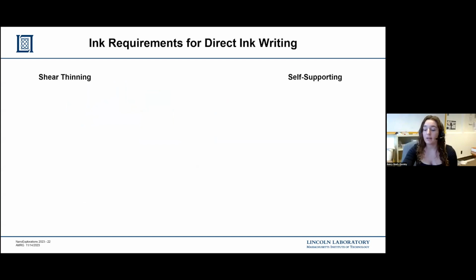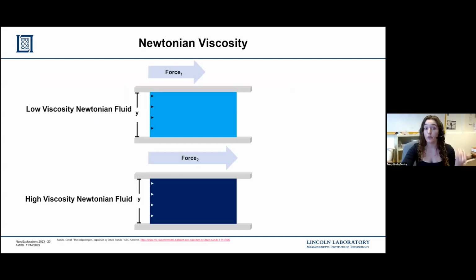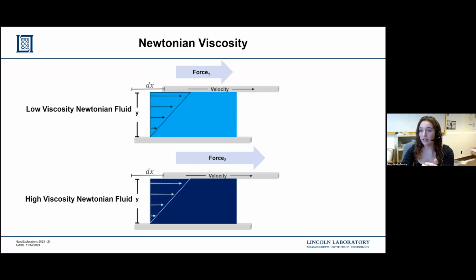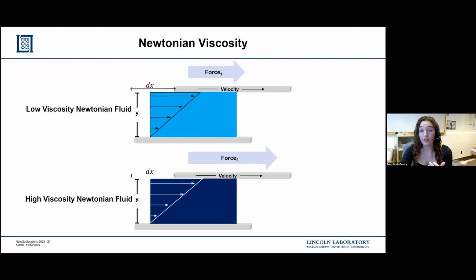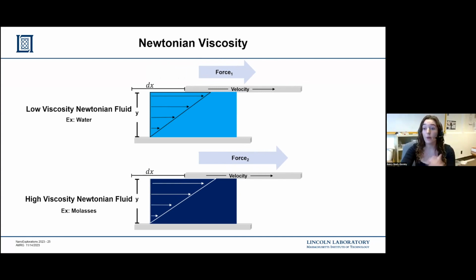So to explain shear thinning, we are going to backtrack into Newtonian viscosity. So if we want to look at low viscosity, which is something like water, or high viscosity fluids, which is something like molasses, we do so in this parallel plate system. So if we apply a force to the topmost plate with the liquid in between and a stagnant bottom plate, we get a velocity of this top plate and it creates this velocity gradient. The velocity gradient is directly proportional to the amount of force that we are putting on. So if we add more force, this velocity gradient grows with it.